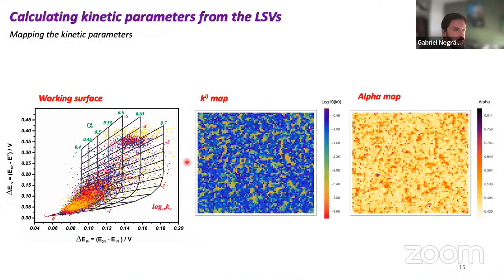So when we do that, we interpolate, and of course there are outliers here. There's interpolation, and there are points that we cannot actually get to the model, and that's just an approximation of the model. But if we look at the K0 map and the alpha map here, we can see that there's a broad distribution. This is in log of K0, of course, but we do have regions that are quite fast, and we do have regions that are actually quite fairly slow.